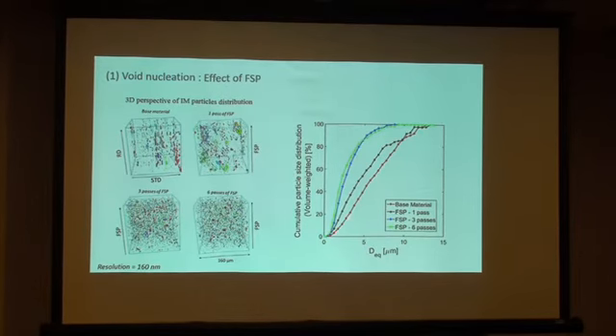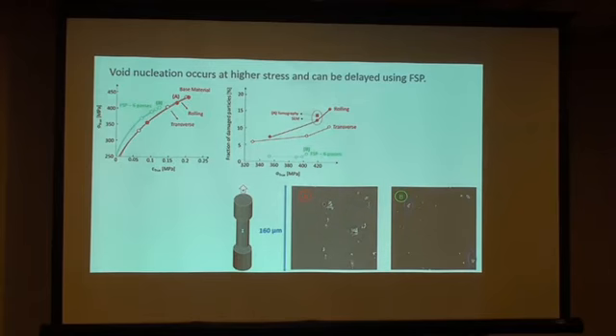So if you look at the size distribution, you see that the base material has a lot of big particles, and then this reduces as the number of passes of friction stir processing increases. This is a typical image from the tomography. Here, in the base material, you see there are a lot of big particles. They are almost always broken. And then here, after 6 passes of friction stir processing, you see a lot of small particles, and from time to time, still a big particle which is broken. And if we look at the fraction of damaged particles, you see that for some level of stress within the matrix, the fraction of damaged particles is highly decreased. So it means that the nucleation is postponed thanks to the reduction in size of the particles.